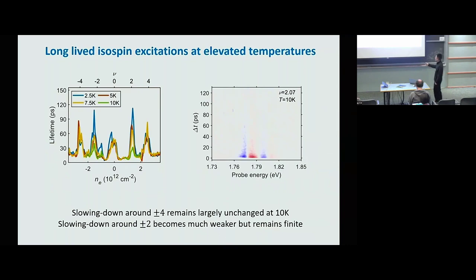At ±4, it doesn't really change over this range, which is not surprising. But at ±2, it first changes significantly, which is probably also not that surprising because they are associated with the isospin orders and fluctuations. But what's probably more surprising is that this slow relaxation still remains there, although much weaker, but still there at 10 Kelvin. And this temperature is pretty high already. It's supposedly well above the ordering temperature of any isospin orders.